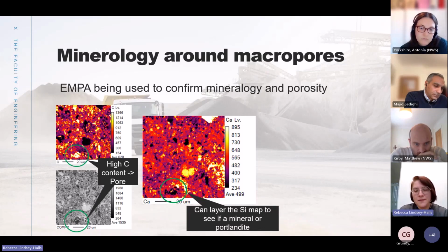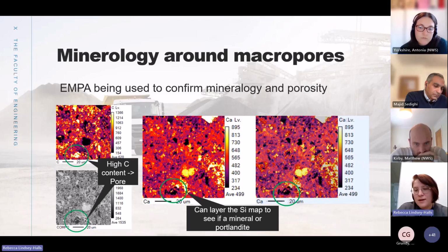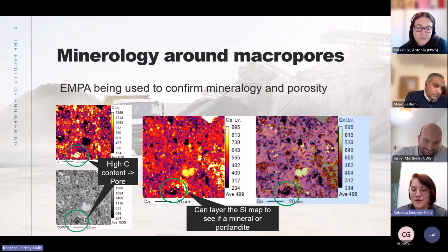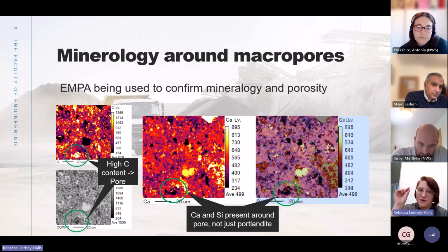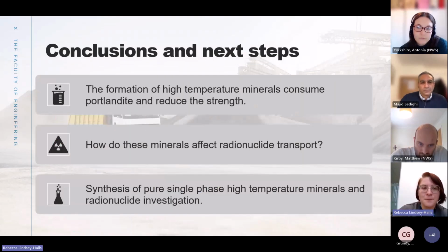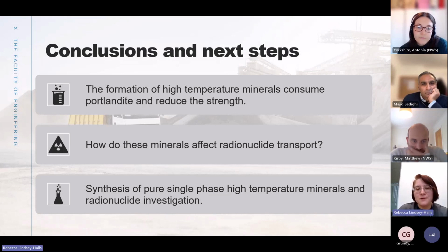or just portlandite forming. And here it is, if you can see, it goes a little bit purply. So this means there is a calcium silicate mineral forming surrounding the pores. So it will be interesting to actually go down there and see what exact mineral is there. The formation of high temperature minerals is consuming the portlandite and reducing the strength.